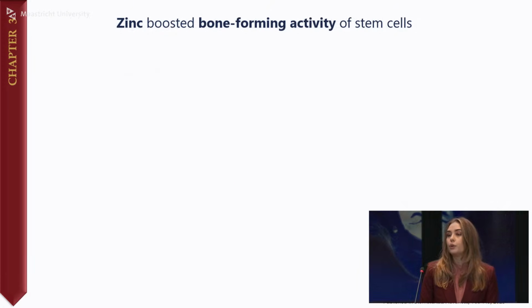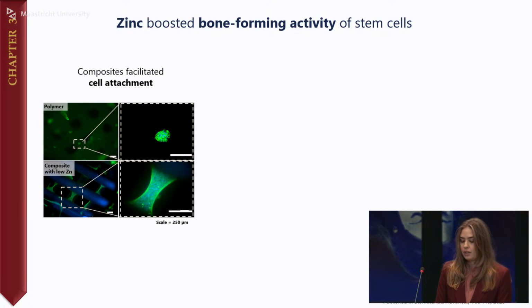What we saw was very promising. We saw that materials containing ceramic supported the cell growth very well. The cells were attaching very well and stretching themselves very nicely. And this means that the material containing ceramics provided a very good structure for the cells to grow on.